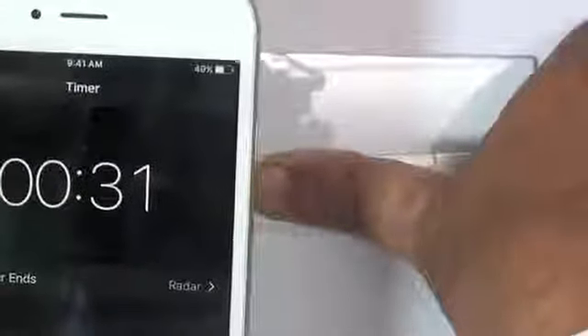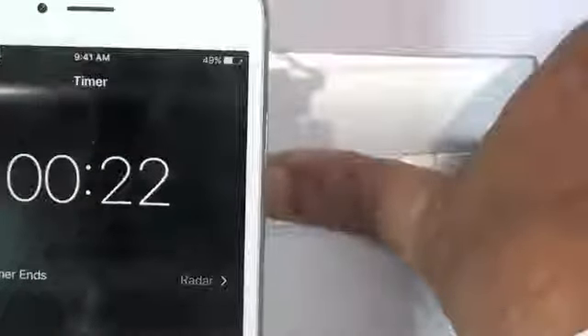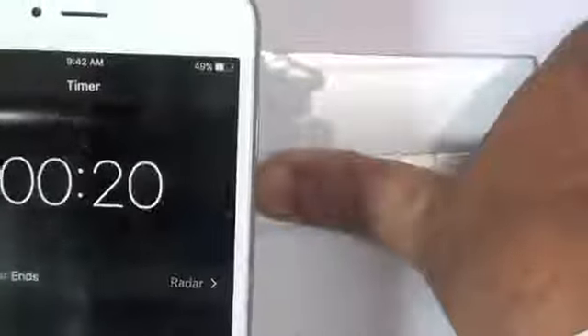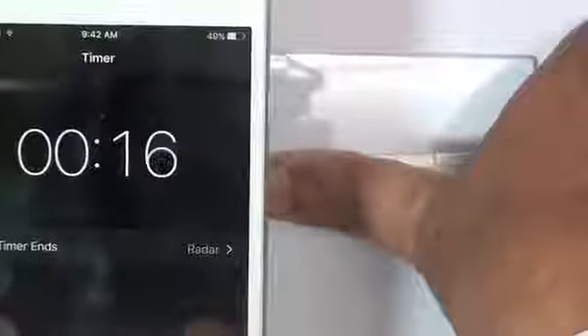It's important to remember that when we apply pressure with our thumb, we don't deform the component. So especially if we are doing this on a thin component, which can deform quite easily with thumb pressure, it's important that we have a solid backing. Something to support it, like the glass plate that we have underneath.